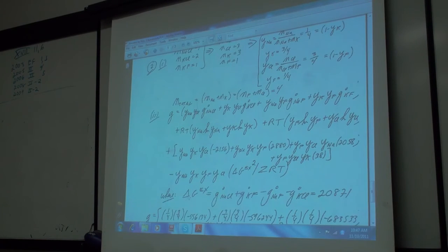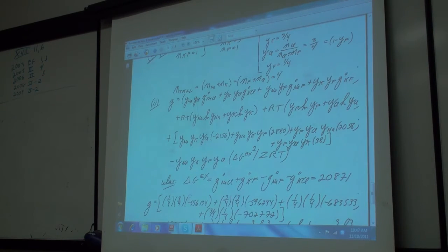Alright. So the two sublattice compound energy formalism with the simple approximation for random mixing is given by this. That's your simple equation with your site fractions times your G naught, your mixing terms. And then you have your alpha terms. So Y sodium, Y potassium, Y chlorine times the excess Gibbs energy term for the sodium chloride potassium chloride system.